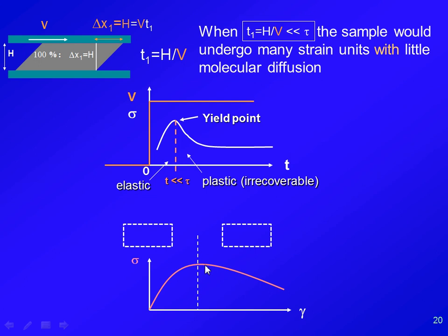But if you shear beyond the maximum and then let stress go free, in other words, turn off the stress, your sample does not recover to its original position. So clearly, there is elastic dominant deformation on the left, and irreversible deformation to the right of the maximum.